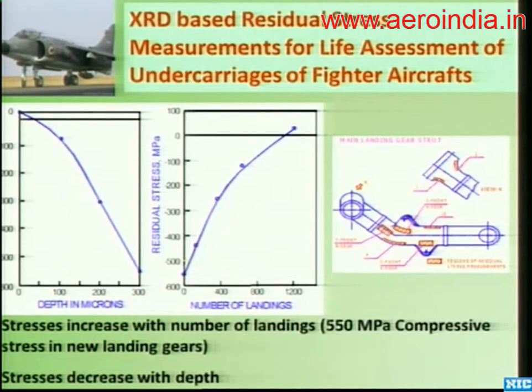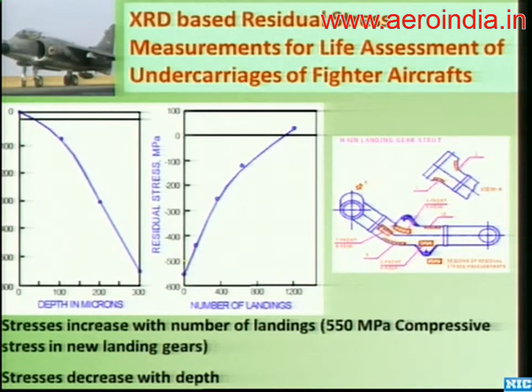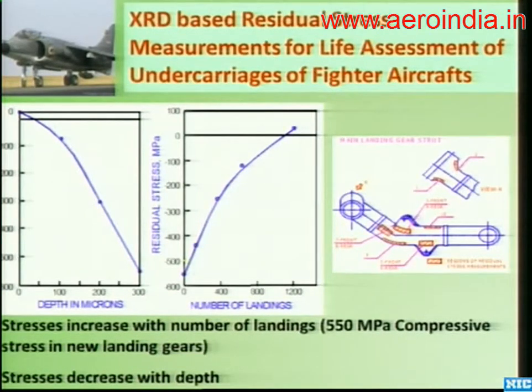The fatigue damage is confined to the top surface of around 300 microns. Taking a life-expired landing gear and removing it layer by layer for residual stress measurements, by 300 microns depth you still see the original high compressive stresses. Two options exist: replace the landing gear after 1,500 landings, or scoop out material in stress-critical regions and apply a re-shot-peening treatment. The OEM design allows one millimeter of extra thickness in stress-critical regions, permitting two regenerations and extending life from 1,500 to 3,000 landings.